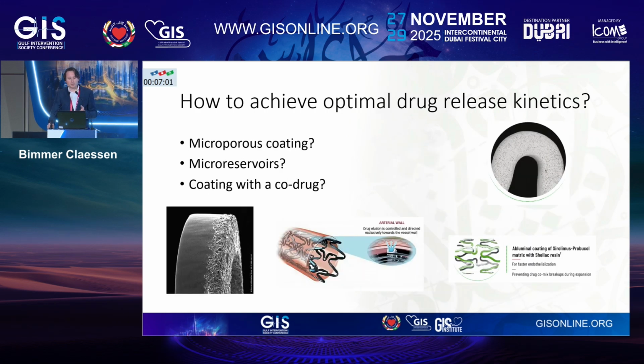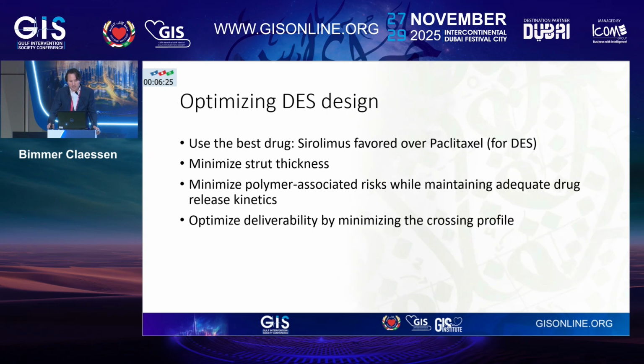So how is it possible to still achieve optimal drug release kinetics while avoiding a polymer altogether? Now, there are several options to do this, and several manufacturers have applied these options. For example, a microreservoir and coating the sirolimus with a more lipophilic drug, for example, fatty acids, as was done with the Cre8 stent. Or in the Vivo ISAR stent, they also use a microporous coating, but also coating with a Probucol co-drug in a shellac resin matrix, which can help to get these optimal release kinetics.